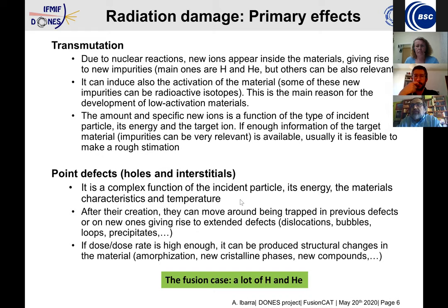The second type of primary effects of the interaction of radiation with material is what we call elastic reactions, and this gives rise to point defects. Due to the interaction of the particle with the ions in the material, these ions are displaced from their position, and they can be stopped in an equivalent position, then nothing happens, or they can be stopped in a position that is not equivalent to this one, and that generates defects in the material. These primary defects are what we call vacancies and interstitials: a vacancy inside the structure of the material, and an ion that is located in a position that is not the right one.